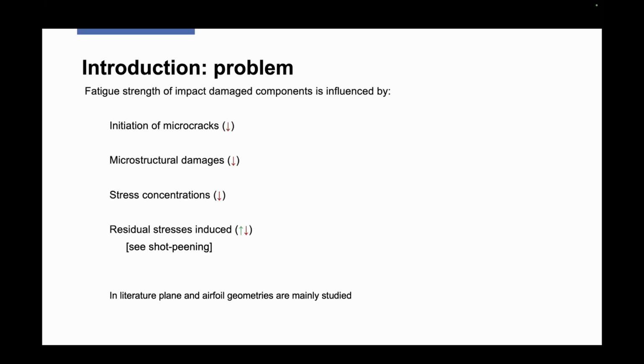In shot peening, you have a global effect, so all the surface of the component is under compression, or the area a little bit below the surface. In the case of foreign object damage or impact damage, you have a localized effect. So you have tensile stresses that are dangerous. In literature, the studies focus on plane and airfoil geometries, as just seen.